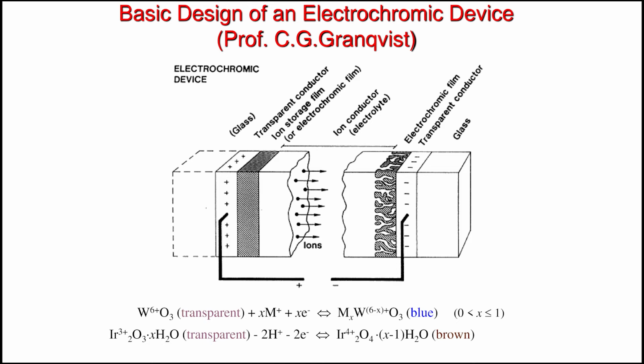I think a more developed model was published by Professor Granqvist, as you see here. He explains that coloration comes through the intercalation of protons or lithium ions into tungsten trioxide, and decoloration is by the deintercalation. In the other electrode, there is a reaction of accumulation of the protons or lithium ions. In this case, the valence of tungsten changes from 6+ to 5+, and it is the so-called polaronic absorption that gives the blue color.